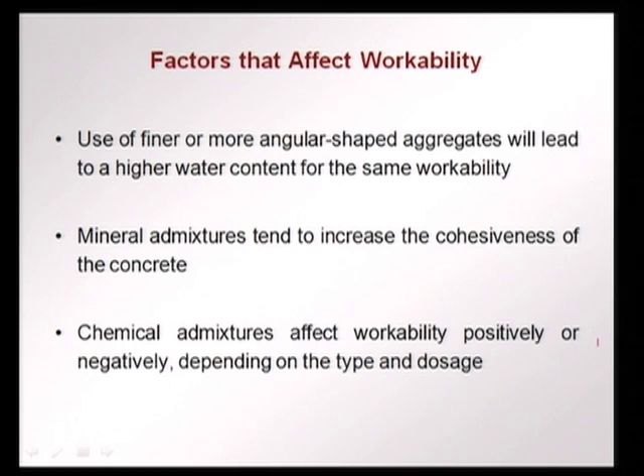We saw that in the case of fly ash, due to the spherical nature of the fly ash particles, you have a ball bearing effect and therefore the flow is better, whereas in the case of silica fume, since the particles are very fine, you have to go for higher slumps in order to compact a structural element properly. Chemical admixtures can affect workability in the way that we want, depending on the type and dosage. If you have a superplasticizer, we already saw that workability is positively affected. We increase the workability for the same water content, or we can decrease the water content for the same workability when we add a chemical admixture. On the other hand, if you have an accelerator, the workability is cut very fast because the concrete starts setting and hardening quickly. So, depending on the chemical admixtures type and dosage, we can affect the workability in the way that we want.